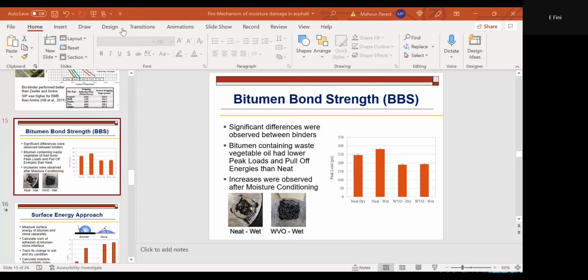You may actually see it in your TSR at a larger scale when the whole thing falls apart, but the initiation is where the weakest point is. So overall, to answer your question, if we are looking at chemistry-driven moisture damage, which is separate from what is caused by pore pressure, there has been a lot of study on pore pressure as a cause of moisture damage, and how the structure of asphalt could promote pressure build-up and cause mechanical damage. That's a comprehensive study of its own.